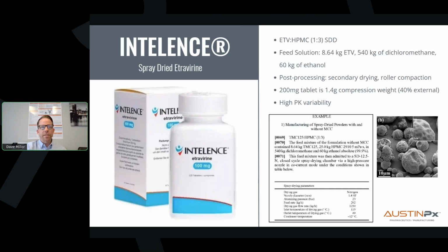So let's look at some of the manufacturing details for the spray drying process. This process really helps to highlight the inefficiencies of solvent-based ASD manufacturing. In order to make that etravirine HPMC dispersion, the innovator had to use 63 kilograms of dichloromethane and 7 kilograms of ethanol per kilo of API. That's just a huge ratio. After spray drying, the product requires secondary drying to remove the residual solvent, followed by roller compaction to improve density, flow, and compressibility. And each of the 200 milligram tablets requires 40% external phase excipients to achieve acceptable tableting properties.